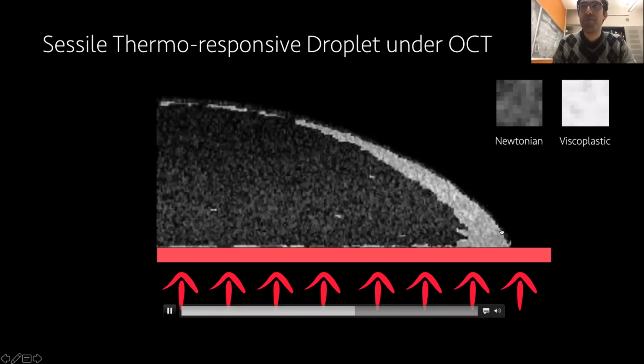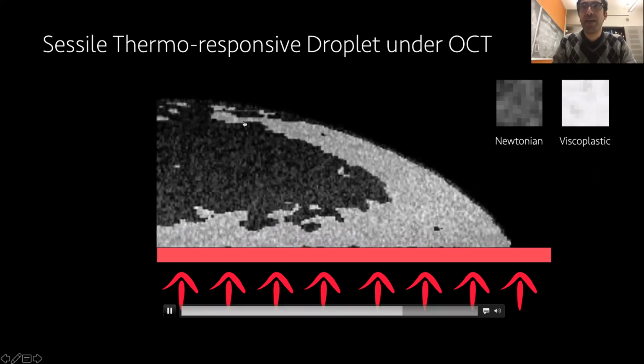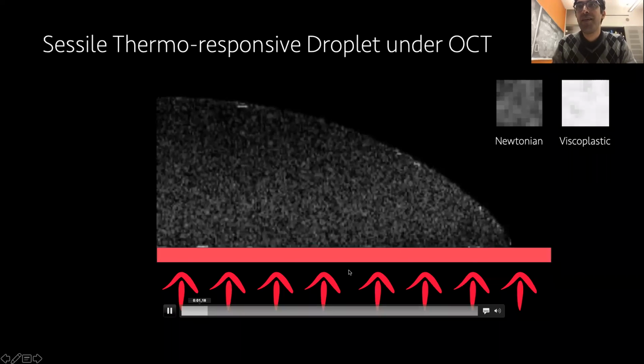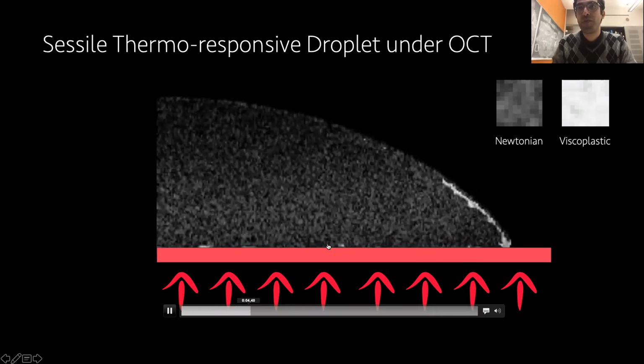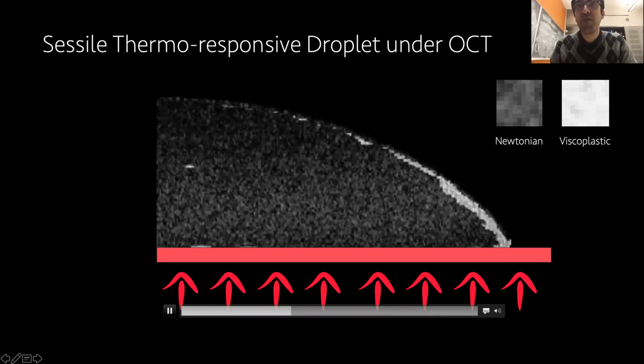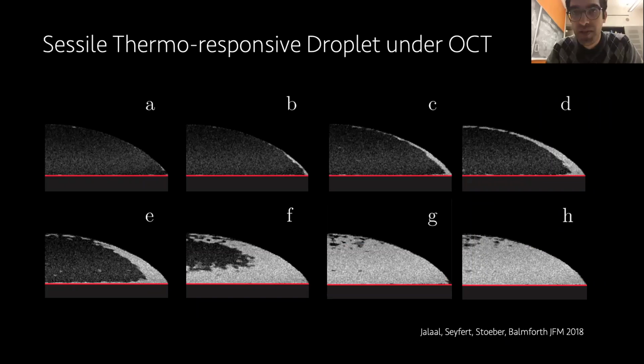It surprised us in the very beginning that, as you also saw, the gelification starts on the interface of the droplet first, and then comes from the heated surface. It puzzled us for a while, but what we found out is that such behavior is because of evaporation. With a little bit of heating, you heat the air, water escapes, polymer concentration goes up, meaning the gel temperature goes down, and your polymer turns to gel. So with this technique, we actually went way beyond what we really wanted to do in these experiments. We found we have in situ measurements of what really happens in a droplet that is changing its phase because of temperature.